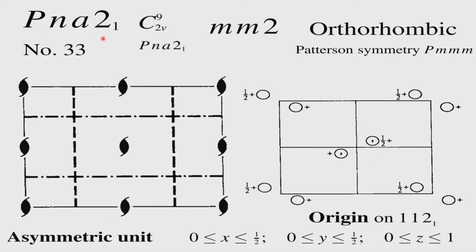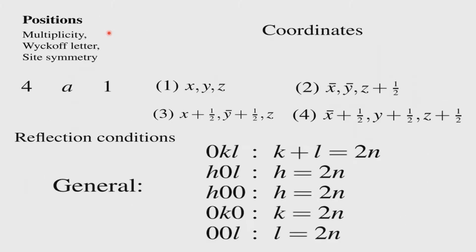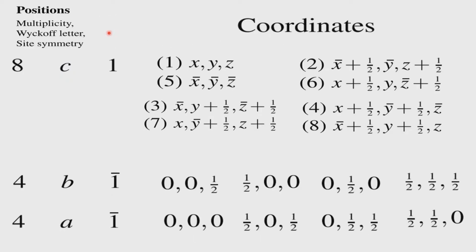When you report in literature, you have to report the space group in which you determined the structure. Within brackets you should say the standard setting is PNA21. It may be very important that this 2-1 axis found in PNA21 has a very special property, like ferroelectricity or ferromagnetism shown in that particular direction, and you want that to be the z axis because your crystal is grown in that particular direction. It is very clearly seen in the morphology of the crystal. Then we would rather maintain that particular space group rather than report the standard space group. So this is something you should bear in mind, and never get into trouble when you discuss this.